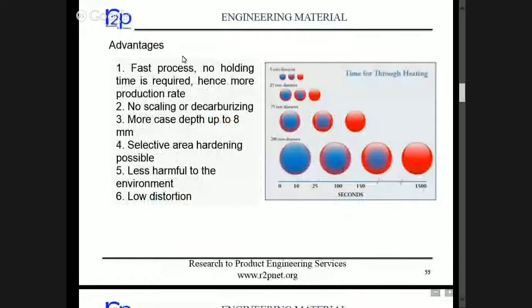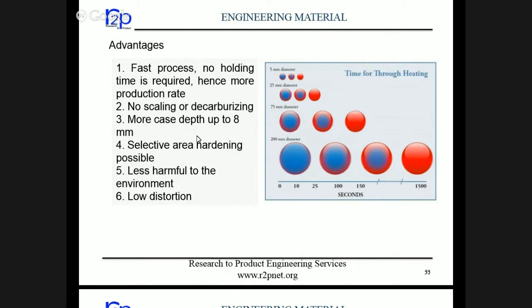So advantages, as we already shared, it's a fast process. No holding time is required, hence more production rate. No scaling or decarburizing. More case depth because carbon even at the lower depths is already available, 0.4 to 0.45. In case of carburizing, we enrich only the outer case only. Here carbon is already there, so if we heat up to the required austenitic temperatures, a case depth of up to 8 mm can also be achieved, while in case of carburizing, up to 1.5 mm is the maximum.